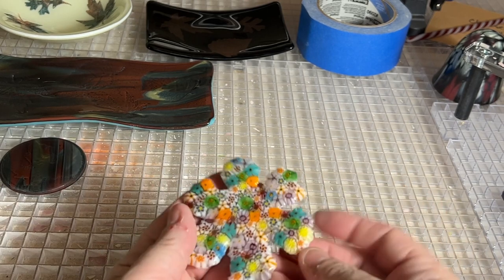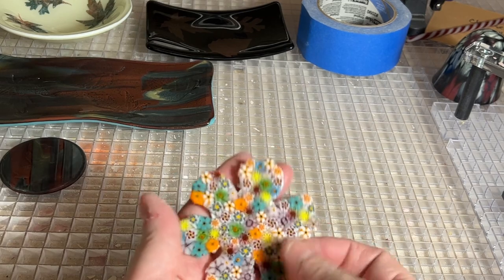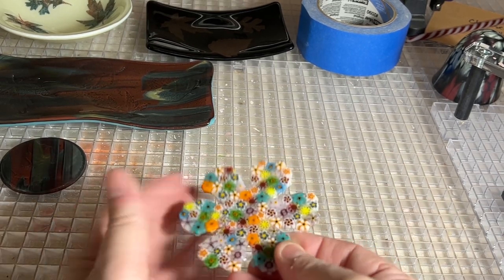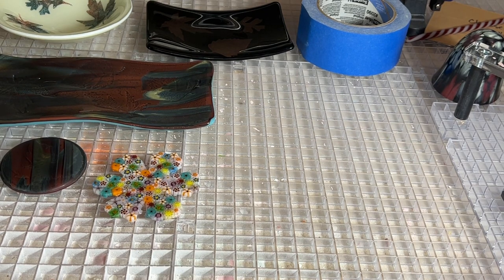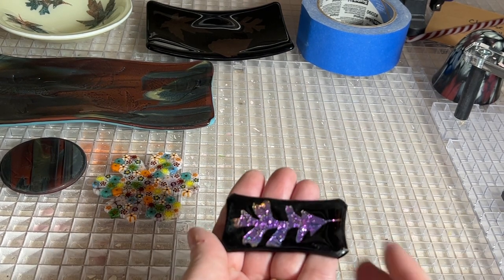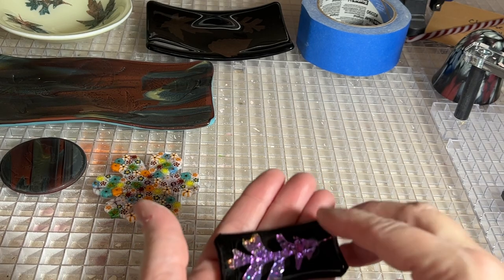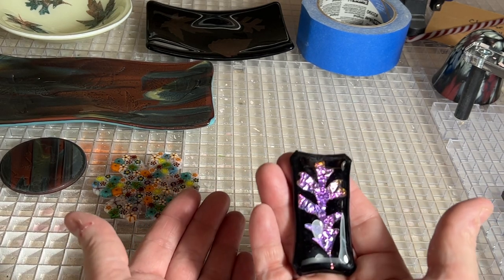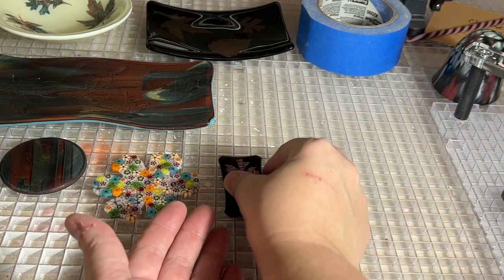This was the underside, so this side is really glossy, but this side is very crisp, and this is the side that I would have up in the next firing. This needed another layer and or less heat because I was using thin, and you can see how it dog boned because, you know, 6 millimeter rule. But it's gonna be easy enough to square that up on the grinder or the lap grinder and just throw it back in for a fire polish.